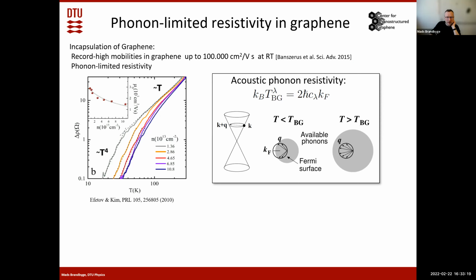So we thought about what happens to the phonon part of the resistivity. In these very clean devices, maybe with nicely encapsulated graphene, you will have a phonon-limited resistivity. The phonons will always be there; you cannot turn these off. So still you can have these record high mobilities in graphene of up to say 100,000 centimeters squared per volt second at room temperature. Maybe today it's somewhat higher even. But of course you always have the phonons there, so it's limited by this.